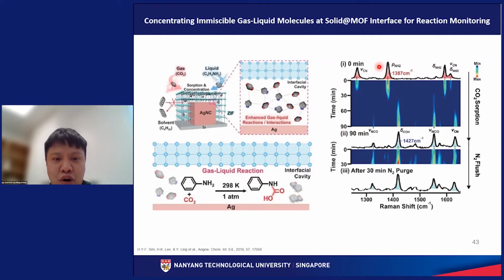Through SERS monitoring, we are able to confirm the formation of carbamate through the reaction of aniline and carbon dioxide. All this process again occurs at 298 Kelvin and 1 atm. Another point to note is that this reaction cannot occur at ambient conditions otherwise, so elevated temperature and pressure is required. The second point to note is that this carbamate species over here is very unstable. So far there is no way for us to extract or isolate this product for characterization. Therefore, this comparison emphasizes the importance of in situ monitoring of reactions, especially when it involves a very unstable product or intermediate.